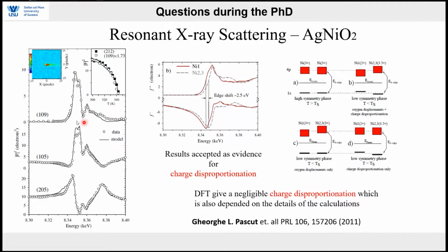So what I'm measuring is this signal here. And this is actually a positive number because its amplitude is f squared, electron squared, that's the units. I'm measuring this for different reflections, then writing the system of how the form factor looks based on each atom. From there, I can extract f prime and f double prime.